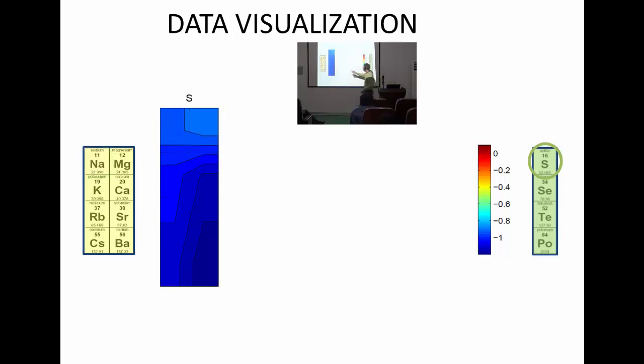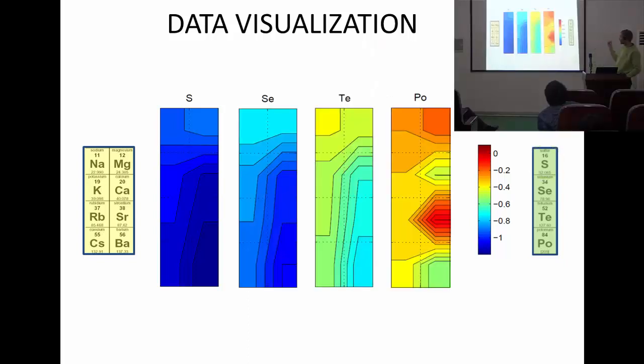That we do for all elements now in this block. So not just sodium, that was here, but for all 8. So what you see here is a combination of 8 of these rectangles, each of them representing 144 different crystals, color-coded with the energy of the most optimal crystal in that set. And that you now do not only for sulfur, but the same story for selenium, for tellurium, for polonium, which are these blocks here. So that gives a first view on what is happening.